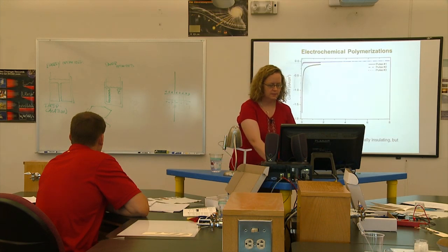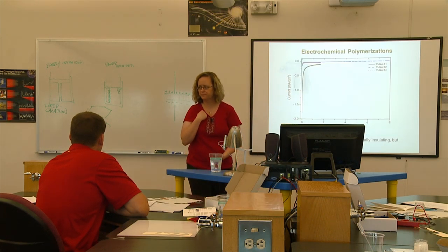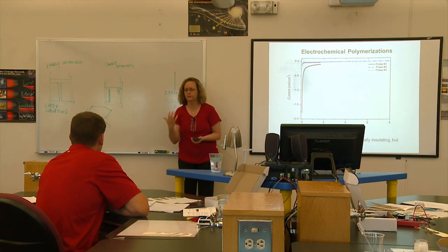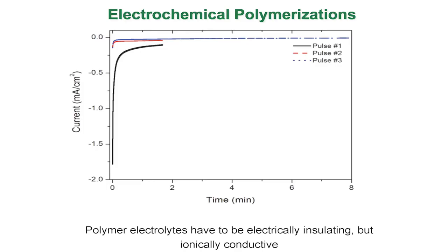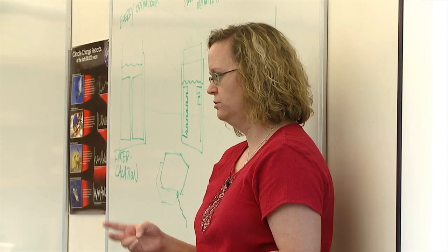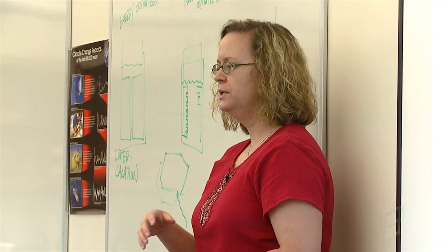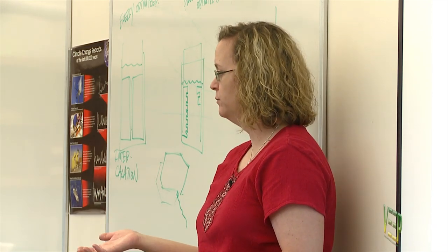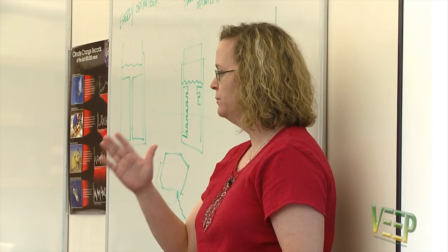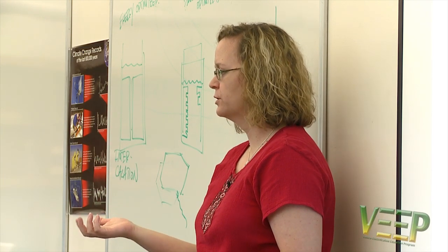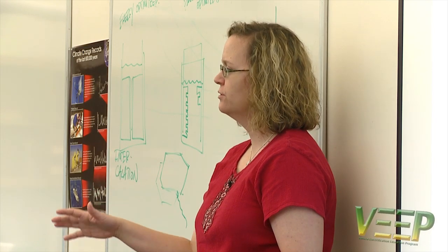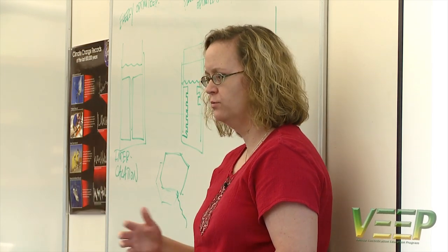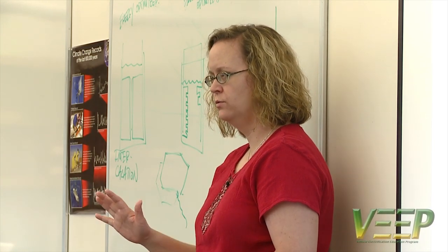That makes sense. But now what we wanted to do was put our polymer on top. Okay, so don't pay attention to the data yet. I'll just tell you again the thinking behind what we wanted to build. So this polymer electrolyte has to be ionically conductive, but electrically insulating. So we were thinking about what the best way was to do that, to coat this high surface area structure. And we decided that electroplating was still the best way, because as you make the polymer, it becomes insulating, and so then no more polymer can grow there. So polymer is only going to grow where there are patches, and if you keep cycling, then you will fill everything, and you will end up with no defects anywhere.